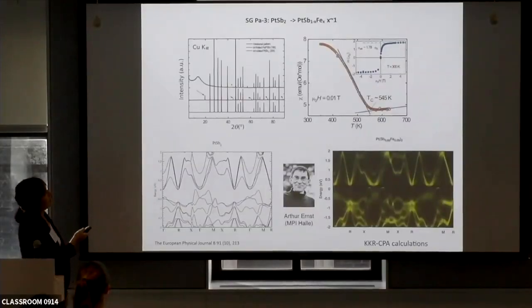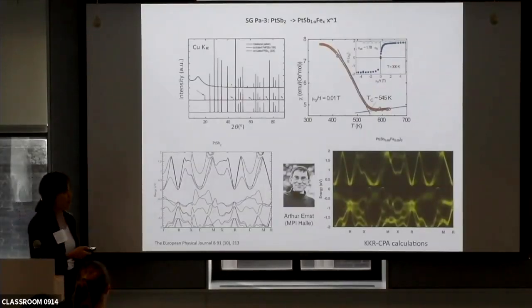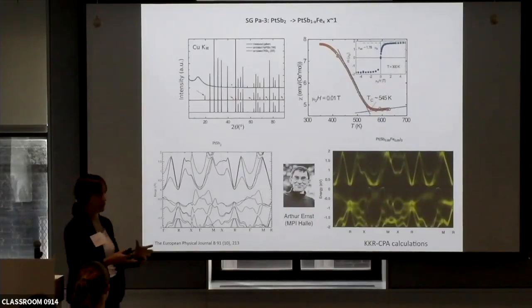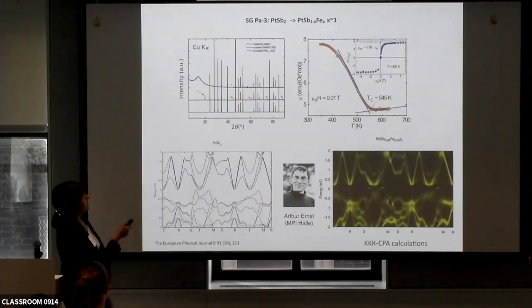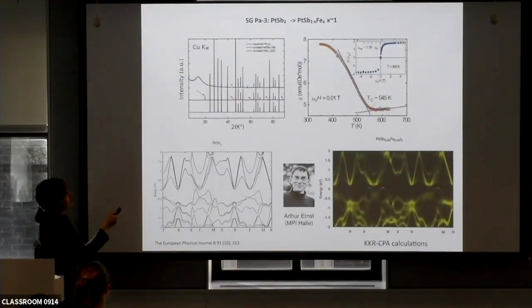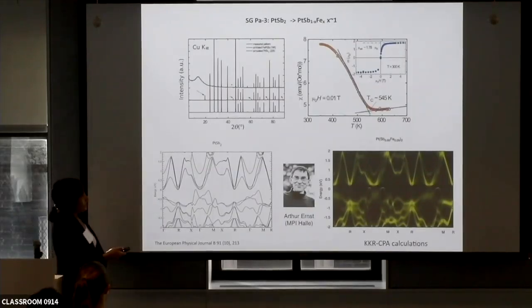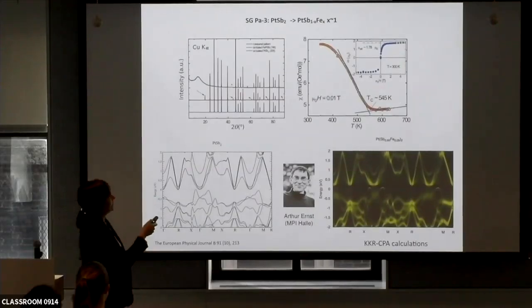Because actually, the original stoichiometric formula we were looking for was a deformation of another space group. And what is really happening is that what we have is originally pyrite, realized in this space group, contaminated by iron. So they did the hysteresis cycle, and they calculated the Curie temperature, and it's ferromagnetic.